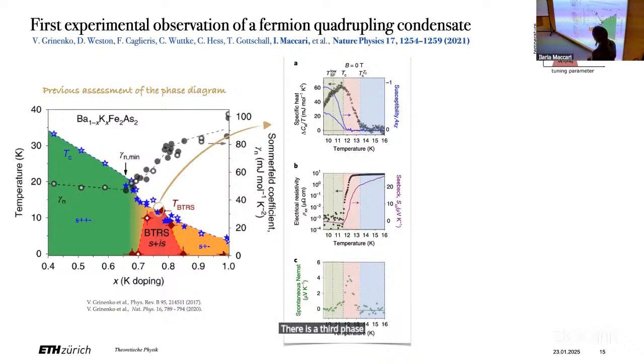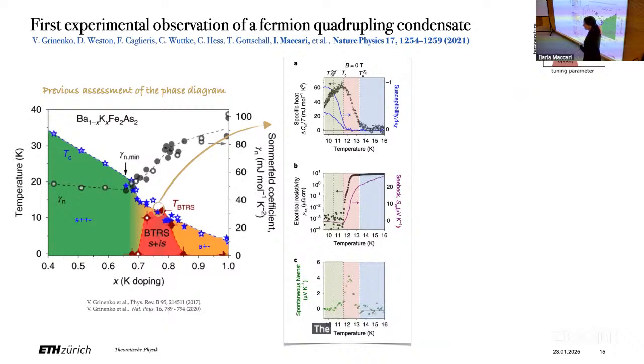A high temperature phase where there is no anomaly in the specific heat, the system is resistive. But in between, as you can see, there is a third phase where one observes essentially an onset of the anomalies in the specific heat. The system is still resistive, and more importantly, one observes a spontaneous Nernst effect, meaning that the system has a spontaneous magnetic field, signaling the spontaneous breaking of the time reversal symmetry.